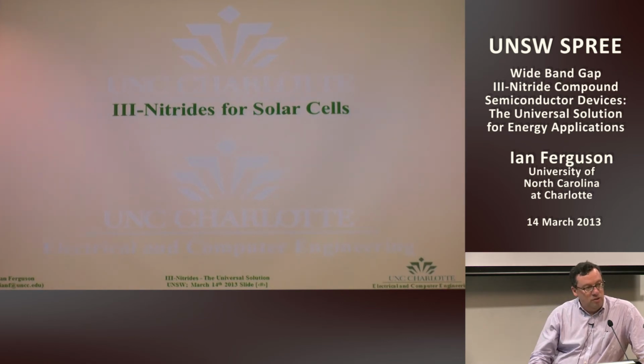And why the nitrides worked there was the fact that you actually did have good PN junctions. You also had materials which were still direct band gap materials. And many people have done this on other tandem cells with gallium phosphide based materials. When you start getting up to the 2 eV region, the devices start going indirect and your layers start getting thicker.